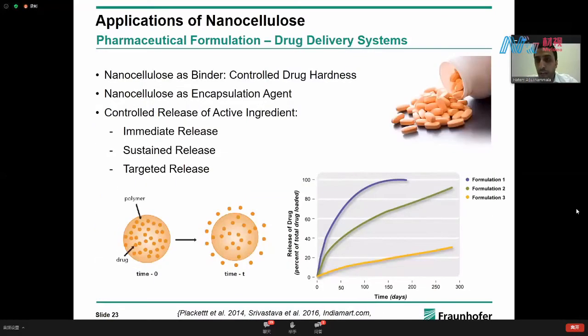In pharmaceutical formulation, nanocellulose is also very interesting for people who work in the pharmaceutical industry. They know that different active ingredients have to be released in very different fashions in our bodies. For example, if you have a headache and you want some paracetamol, you would love it to be released immediately. But other medicines have different release systems, and they might need to be released in doses, or delayed, or targeted. This requires so much energy and time in the pharmaceutical industry to optimize delivery systems for different active ingredients. And nanocellulose here is very interesting because it can act as a binder, improving the mechanical properties of tablets. There's a really direct relationship between tablet hardness and drug release. Also, nanocellulose can work as an encapsulating agent, so the active ingredient can be encapsulated inside and then released at a certain time.